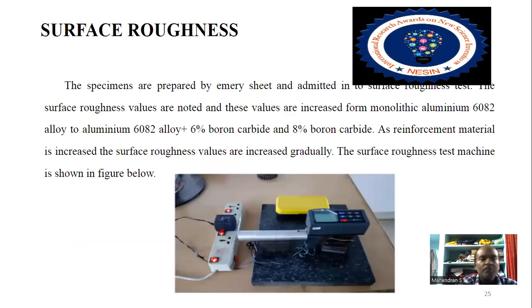Next one is surface roughness. The specimens are prepared by emery sheet and subjected to the surface roughness test. The surface roughness values are noted. These values are increased from monolithic aluminum 6082 alloy to aluminum 6082 alloy plus 6% and 8% boron carbide added. As reinforcement material is increased, the surface roughness values are increased gradually. The surface roughness test machine is shown in the figure.